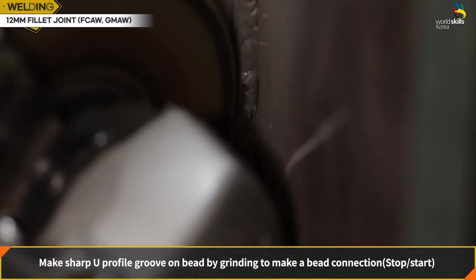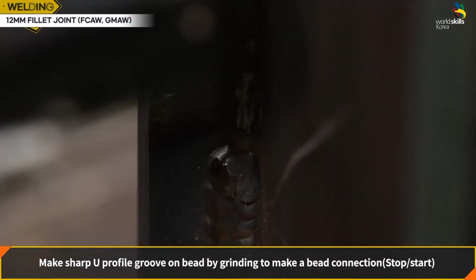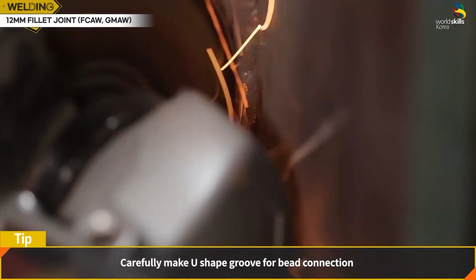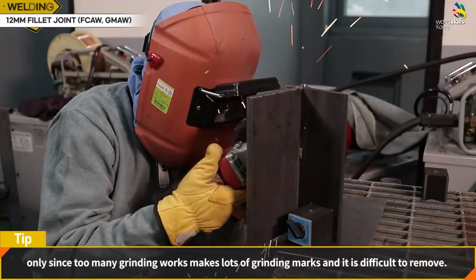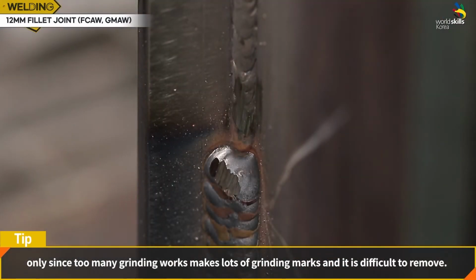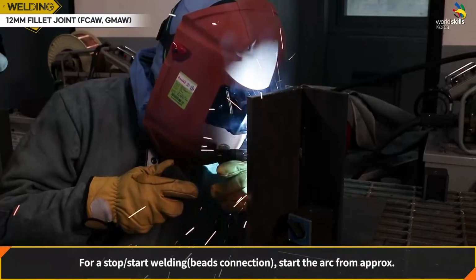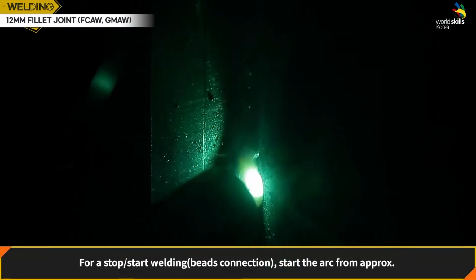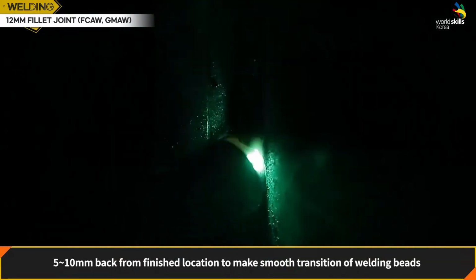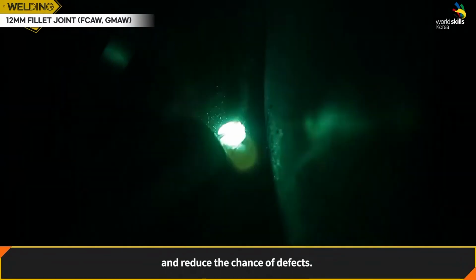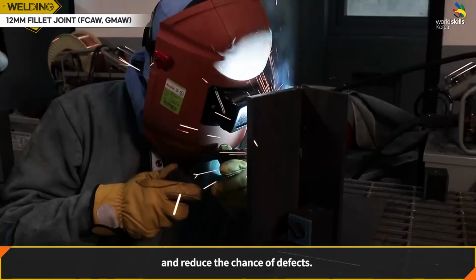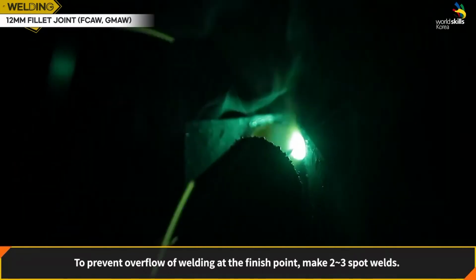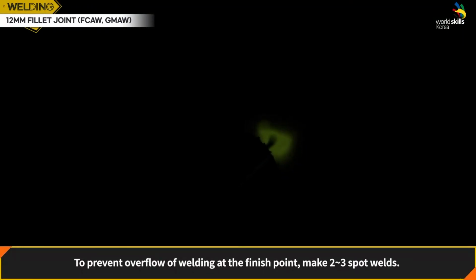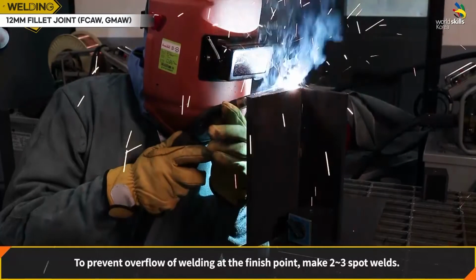Make a sharp U-profile groove on the bead by grinding to make a bead connection, stop-start. Carefully make the U-shaped groove for bead connection only, since too much grinding makes lots of grinding marks, and they are difficult to remove. For a stop-start welding bead connection, start the arc from approximately 5 to 10 millimeters back from the finished location to make a smooth transition of welding beads and reduce the chance of defects. To prevent overflow of welding at the finish point, make 2 or 3 spot welds.